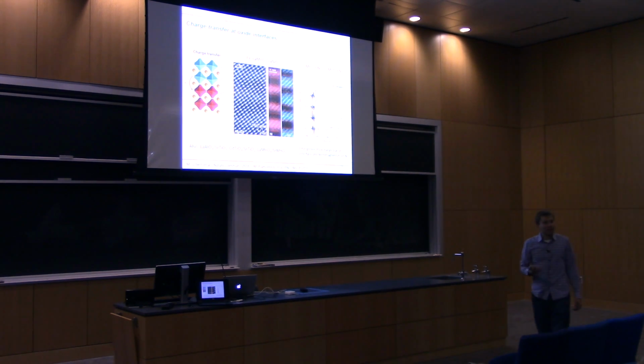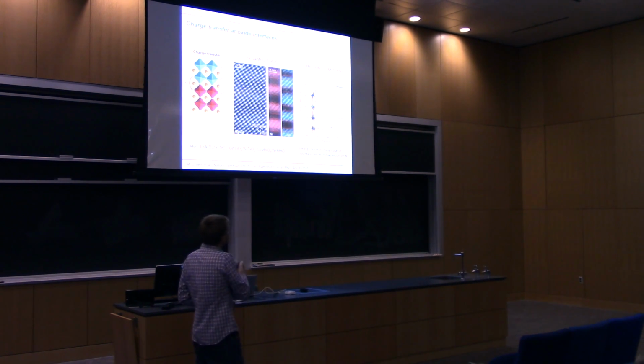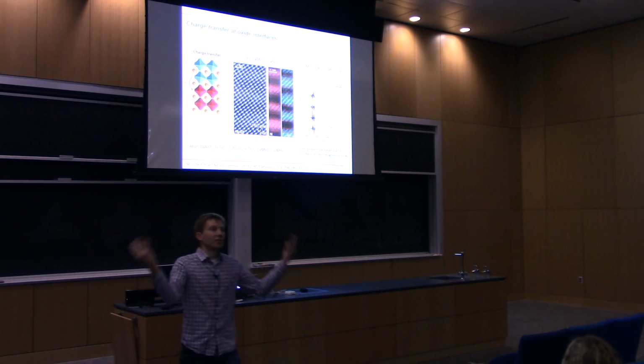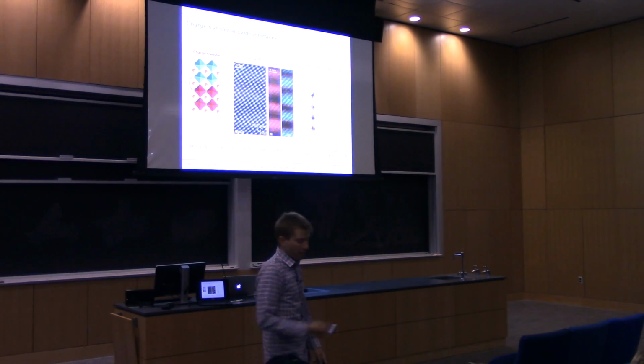And this nickel 2+ then is ferromagnetically coupled at the interface. You see some XMCD signal on the nickel. It looks like 2+. And so you get this emergence of the exchange bias at the interface and ferromagnetism on the nickel because you have this charge transfer. Away from the interface, it's just paramagnetic lanthanum nickelate.